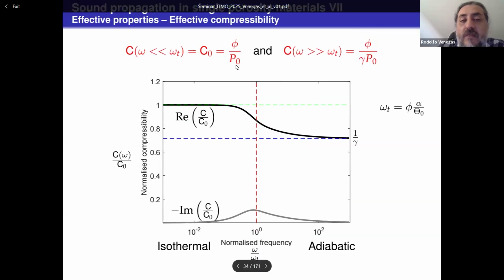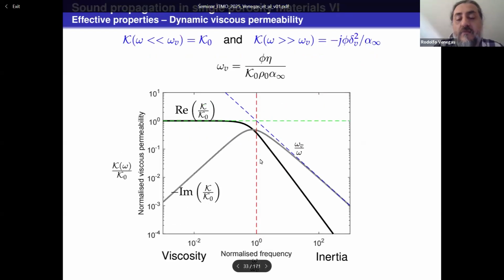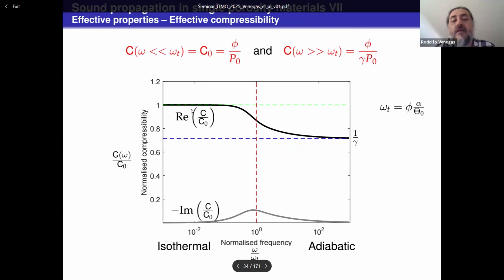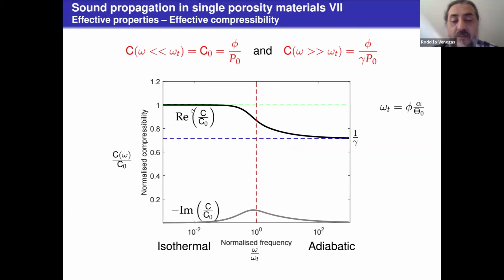In a similar way, these are the low frequency and high frequency limits of the compressibility. Around this thermal characteristic frequency, you have a small peak in the imaginary part that shows that the dissipation of energy due to heat conduction is maximum around this frequency. So below this thermal characteristic frequency, we are in an isothermal regime, and well above, we are in an adiabatic regime. So this is the classical behavior of the dynamic viscous permeability, and this is the classical behavior of the effective compressibility.